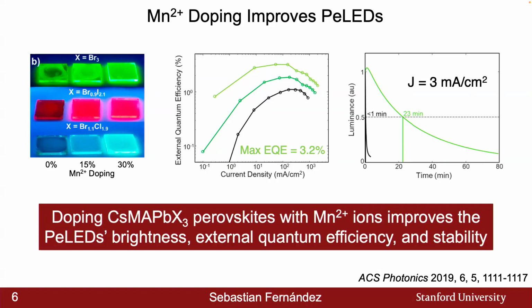And this was a fantastic first step, but unfortunately these external quantum efficiency numbers and the stability are not as high as they need to be in order to enable this lighting technology. The primary reason for this is that there is still a high density of surface defect states that are reducing the amount of radiative recombination that can occur within these thin films.